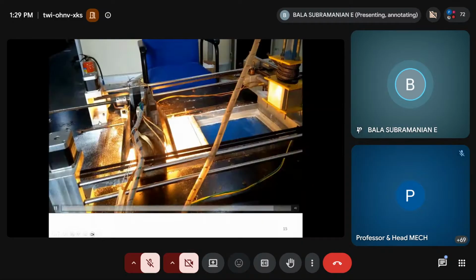Okay, material. Our nozzle diameter for deposition was 0.4 mm. As for the nozzle material, because we are delivering only liquid, we used a standard polymer material, whatever conventional polymer-based nozzles are available for FDM. That was what was used.